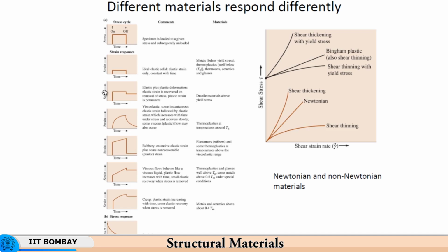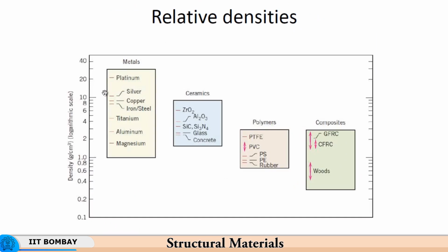So, here this is a completely different situation. The material is deformed to a certain constant strain, and the stress level keeps dropping. So, supposing you have loaded a sample, as in thermoplastics, you load them up to a particular strain level and leave it at that, the stress level will continuously decrease due to relaxation of these polymer chains. So, basically these are the different responses of the material, and that is exploited in actual use for different applications. That is what I wanted to emphasize by this.